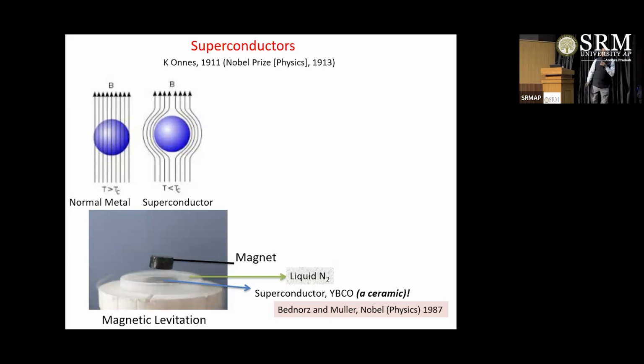So one of the very interesting properties of a superconductor, for example, lead is a reasonably good superconductor. Niobium is a good superconductor with tens of kelvins of temperature. Above Tc, they behave like a normal metal. If you apply a magnetic field, it will just pass through them. But if you lower the temperature of this material below a certain Tc, they become superconductor. It means not only do they have 0 resistance, but magnetic field cannot penetrate that material. The very unique property is called Meissner effect or perfect diamagnetism.